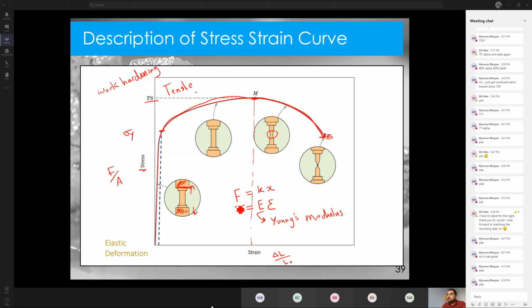So before that point, before the point M, for these strains, the deformation was uniform. The sample had a uniform cross-section. It was thinning uniformly and getting longer uniformly. Past this point, you could see this region here was thinning a lot more than the regions up here. So the deformation is no longer uniform. So this strain here is called also the maximum uniform elongation, because beyond it, the deformation is non-uniform. And then the last point we get is this strain here, which is the fracture strain. So it gives us an idea of the ductility of the material.